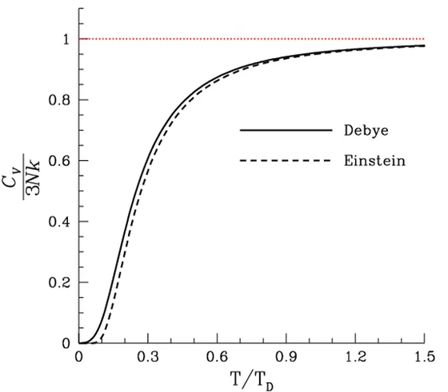Thus, it is the heat capacity per mole of atoms, not per mole of molecules, which is the intensive quantity, and which comes closest to being a constant for all substances at high temperatures. This relationship was noticed empirically in 1819, and is called the Dulong-Petit law, after its two discoverers. Historically, the fact that specific heat capacities are approximately equal when corrected by the presumed weight of the atoms of solids was an important piece of data in favor of the atomic theory of matter.